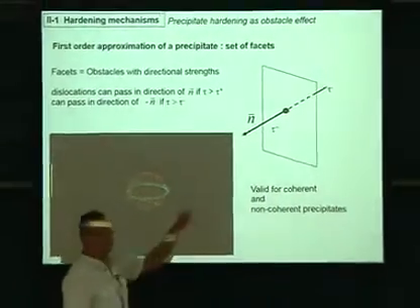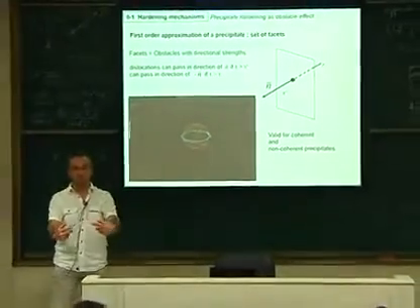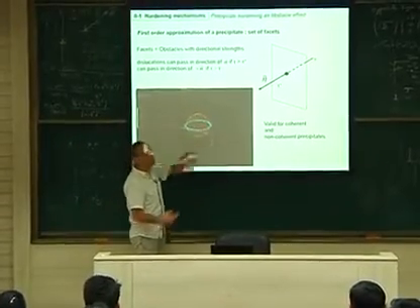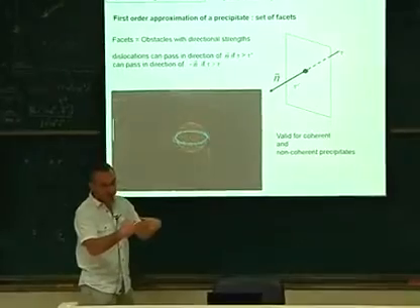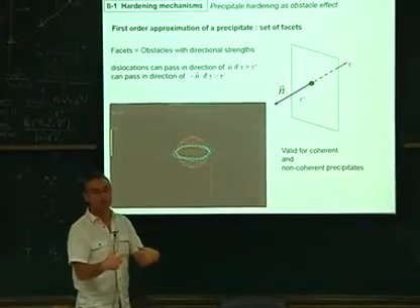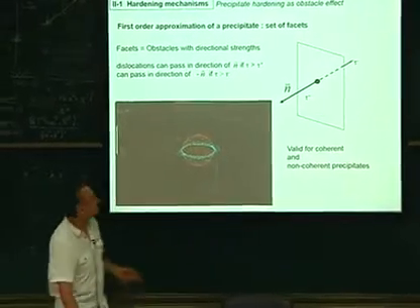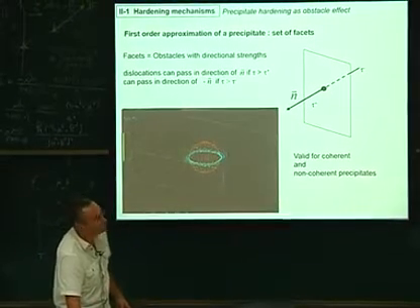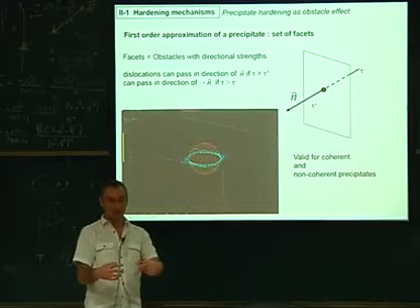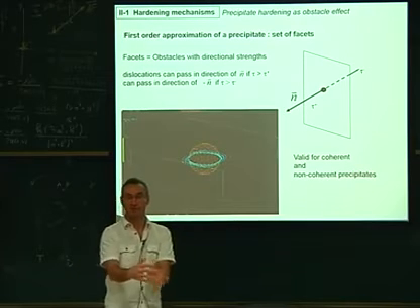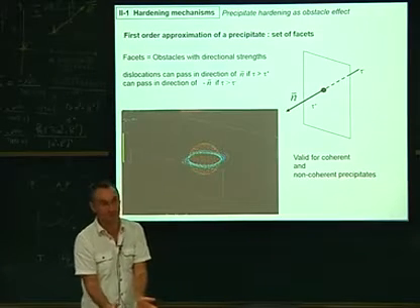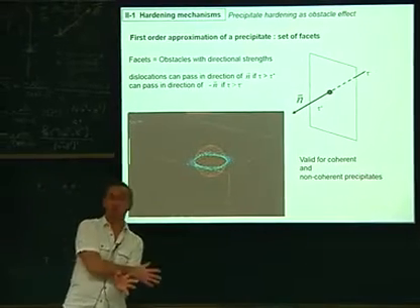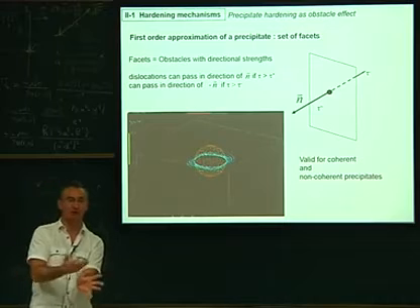And I say, okay, these facets, now for the dislocation is an obstacle. So when a dislocation comes in front of the facet, like here is a set of facets, it will be able to pass through the facet if the local stress is above a critical value. So there is a critical value associated to the facet. So actually we have 2 critical values, one to pass through in that direction and one to pass through the other direction. So that way you can have some easy shear, and then you can be trapped, you can make a trap in your dislocation dynamics code. We call it a trap. If you want not the dislocation to come back when you reverse the loading, for example, you can make a trap. They can cross easily and they cannot come back.